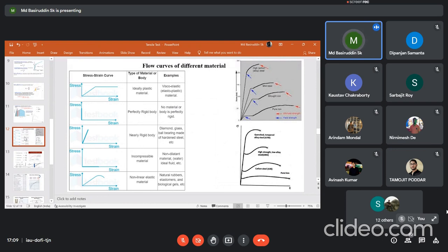let's say initially you have taken a 100 by 100 by 50 dimension specimen, where 50 is the thickness of that particular material. And the second material you have taken, just by rolling or reducing the thickness of the initial material, let's say you have reduced the thickness by 10 mm, and the third one you have taken where the final thickness is 20 mm. So that means for the third material that you are using, you have given the maximum amount of deformation to that particular material.